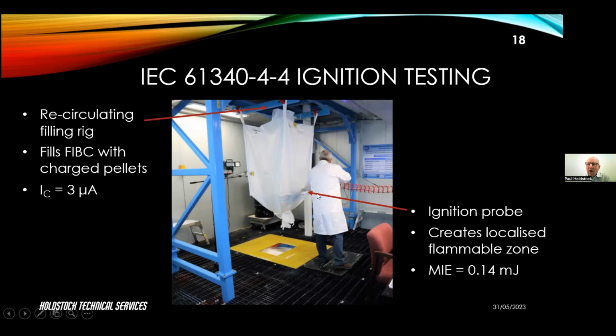So the operator brings the ignition probe up to the bag as it's being filled with this charging current of 3 microamp. Doesn't just do that once, he has to test at least 50 positions on each side of the bag. Also any spouts, or top spouts and bottom spouts, and any labels or other attachments to the bag. So typically we'd be looking at around 250 approaches, and we do that at both low humidity and high humidity. So that's about 500 approaches, and to pass that test you have to go through all that testing with no ignition. One ignition alone will cause the bag to fail. So this really is proving the safety of Type D FIBC.